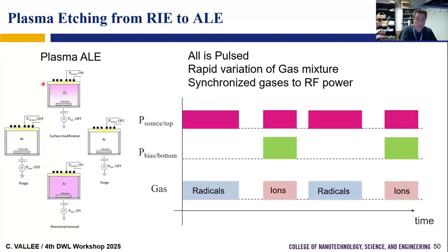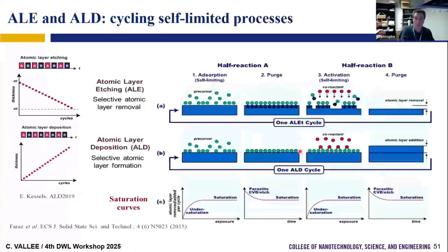So we not only modulate the ion flux, but maybe we can vary the ion flux with time by pulsing the gas. And if we pulse the gas, and if we have an HDP source, we only apply power to the source when we have radicals, so we have a chemical etching, a sort of radical etching process. We only throw radicals to the surface, and then after we apply a bias to have energetic ions. So we have ionic flux with energy, and we can pulse to have successive steps of radicals and ions, and this is where we go for atomic layer etching.